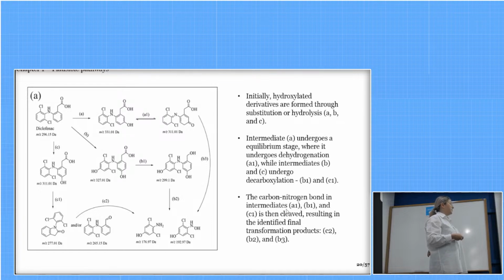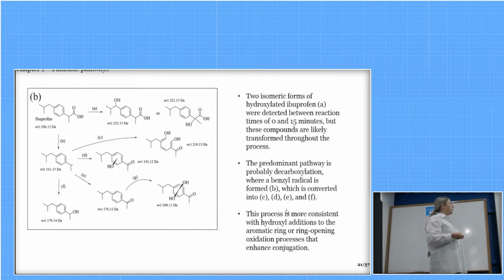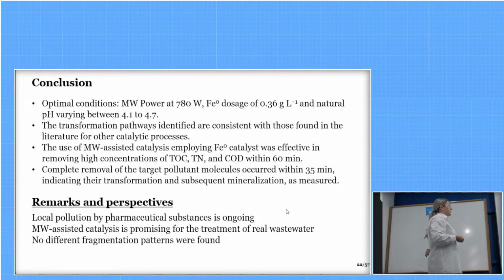We then studied the possible pathways for diclofenac, and we observed similar patterns to what the literature reports, and for ibuprofen the same patterns. So our conclusion from this study was that the optimal conditions were using a considerably low microwave power of 780 watts, while a conventional oven uses about 1,200 watts, the catalyst dosage of 0.36 gram per liter, and the natural pH between 4.1 and 4.7. The transformation pathways identified were consistent with the ones found in the literature for other catalytic processes, so we did not produce any other recalcitrant byproduct than the ones already reported.